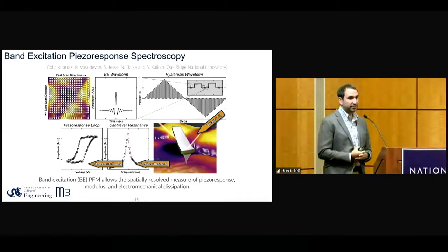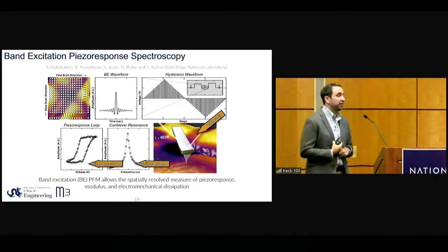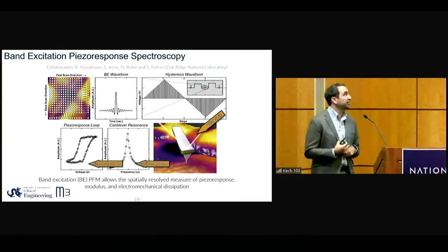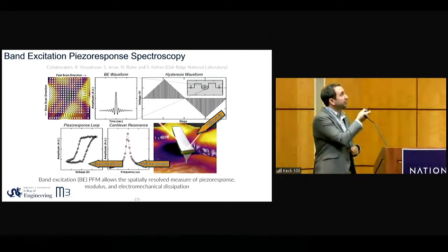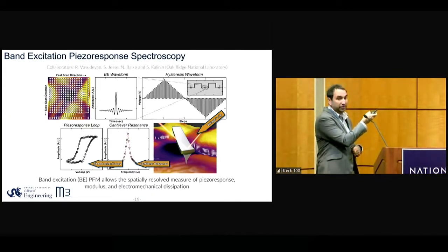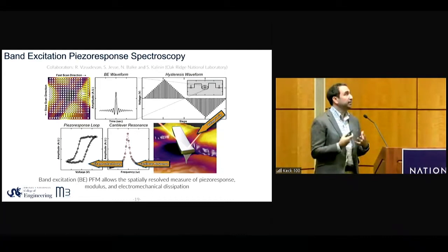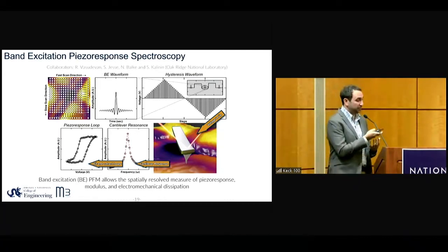So we do this experiment that's very common called band excitation piezo response force microscopy. It's developed out of Oak Ridge National Lab. The key point is that at every single pixel position, we apply a bipolar triangular waveform that switches the material, and then you're measuring the dynamic response of that material, the cantilever, by measuring the cantilever resonance at a band of frequencies.